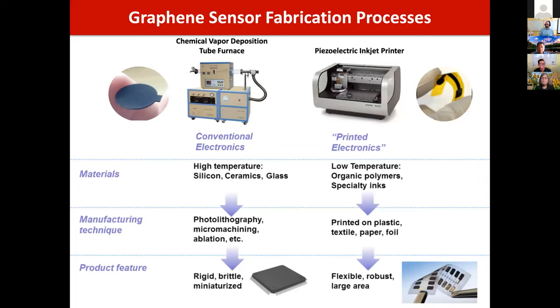So what we've moved towards is making high yield graphene, just exfoliating flakes of graphene from graphite and then putting them into a solution form and printing them. And we can print them through a wide variety of techniques. We don't maintain the incredible electrical conductivity and other material properties of graphene, but it's good enough for sensors. And it's a carbon-based material, so it's biologically friendly. We can bind biologicals to them quite easily. And we'll show you that we can change that surface structure so that it's more electrocatalytic for electrochemical sensing and has more surface area to bind biorecognition agents to it.